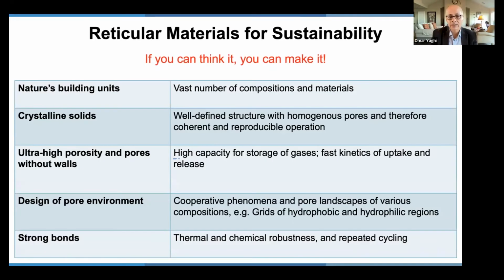And so if you just look at what these materials and the way we make them allow us to do in terms of sustainability and in terms of making devices, let's just look here on the left. We use nature's building blocks, minerals and organics, to make a vast number of compositions and materials, almost infinite, that you can choose from. They're crystalline, so they have well-defined structures, homogeneous pores, and therefore they have reproducible operation. They have ultra-high porosity, and their pores have no walls. That gives you very high capacity for storage of those gases and fast kinetics. So fast kinetics for uptake and release of those gases so that the cycling is fast. You don't have to wait too long to take up, let's say, hydrogen or CO2 and take it out. So that, again, impacts the